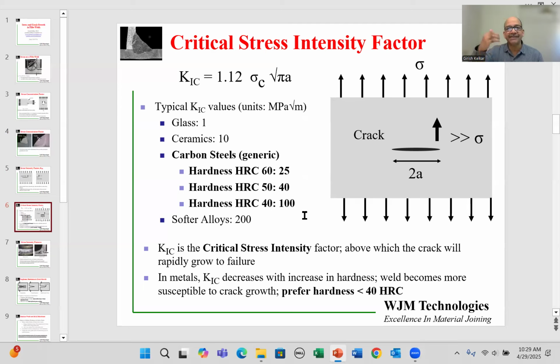So K1C is the critical stress intensity. Once you reach that value, then the crack starts growing and then it is impossible to stop. So that is a critical value where the crack starts growing and leads to failure. Soft alloys are 200, and basically it's very difficult for the crack to grow in these alloys. So we have to keep in mind, because most of the time we are welding structural alloys where there is some amount of hardness, what we need to do when we are welding is try our best to keep the hardness below 40 so that we have a high enough critical stress intensity factor.